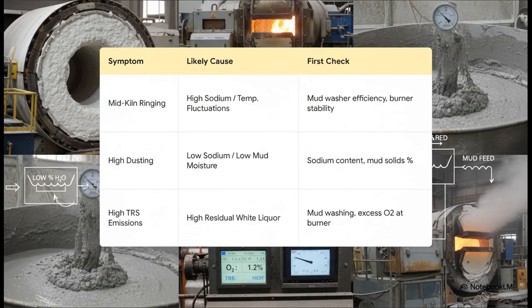So you see a ring forming mid-kiln. Your first thoughts should be high sodium or temperature fluctuations. So go check your mud washer efficiency and look at the burner stability trends. Lot of dust. That probably means your sodium is too low or your mud is too dry. Check your sodium levels and your mud solids percentage. High TRS emissions, that's total reduced sulfur. That's almost always unwashed white liquor getting into the kiln. Check your mud washing again and check the excess O2 at your burner. It's a very straightforward, practical way to diagnose problems.